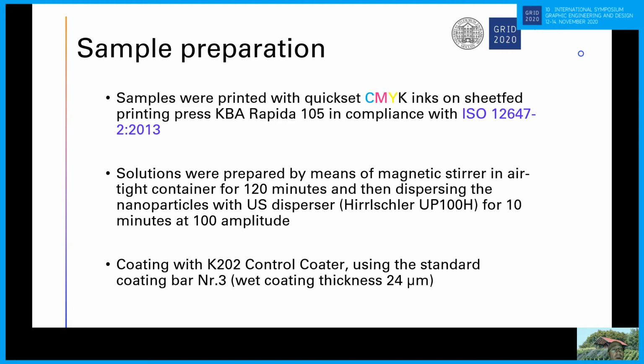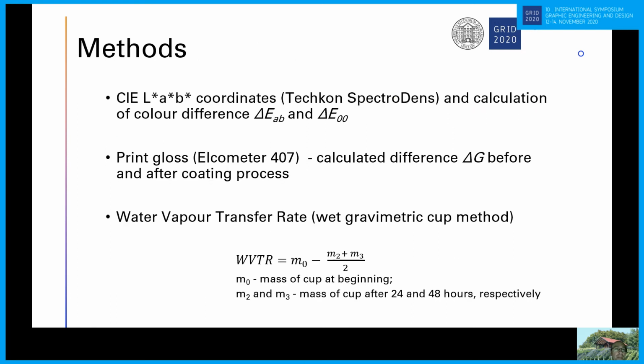The dispersing of nanoparticles was done prior to applying them on the print with an ultrasound disperser for 10 minutes. The coating of the prints was done by using the K202 control coater, using the standard coating bar number 3. That means that the wet coating thickness will be 24 micrometers, and the coating was done by applying always the same pressure and the same coating speed.